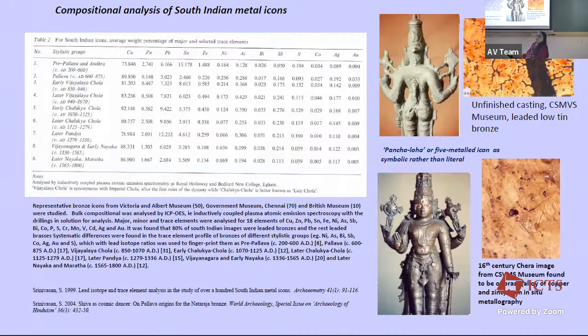So I had undertaken to sample about 150 representative images from different museum collections, the Victoria and Albert Museum, Government Museum Chennai, and so on. And then, of course, undertaken analysis for 18 elements using inductively coupled plasma optical emission spectroscopy. So there were about 18 elements that could be analyzed. And from that, you could sort of build up some trends for the different stylistic groups of bronzes, such as